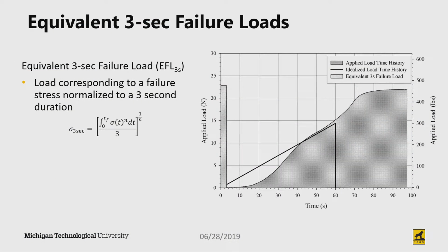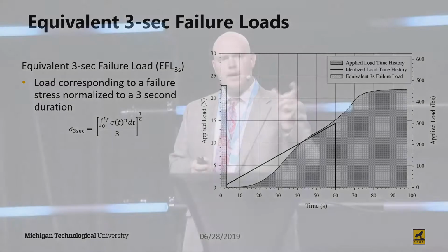Before we do that, one of the key things we know is that when we propagate a crack until it becomes a critical flaw that actually initiates fracture, there is a time element to that. So if I apply the same load over a very short versus a long period of time, I'm going to get a different break time or fracture failure load magnitude.